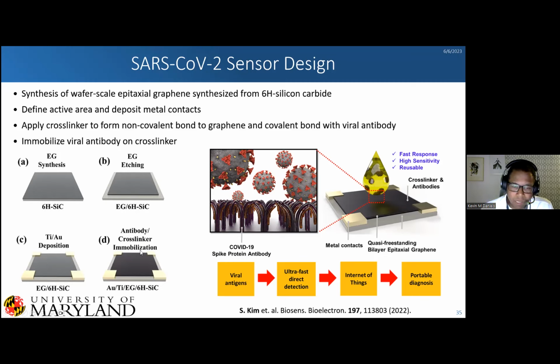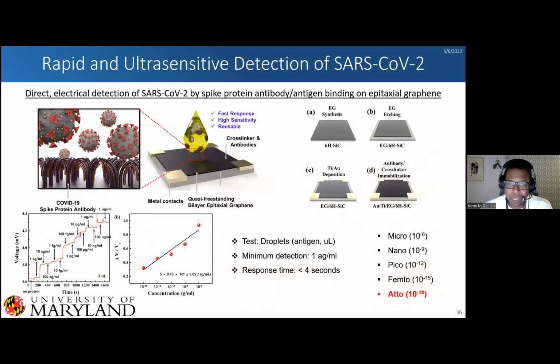And then we put a crosslinker. This is a poly-L-lysine crosslinker that forms covalently with the antibodies that we put down and non-covalently with the graphene. Because as I said before, if you form covalent bonds with graphene, you kill the conductivity, you kill the mobility almost immediately. So we didn't want to do that. And so really we're kind of interacting with the pi bonds meaningfully with each binding. And so we got some really interesting results.